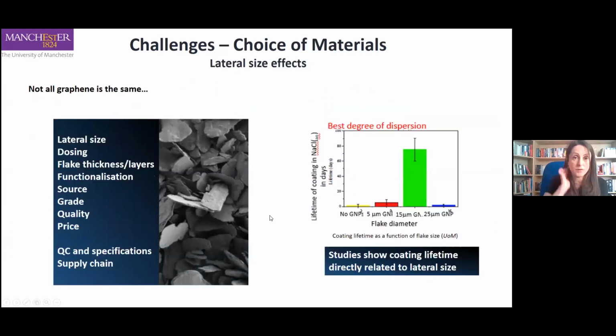And here we're talking about choice of materials again. This is what I referred to just before. It's how the lifetime of a coating is affected by different flake sizes. So this is lateral size. This is work that was done at the University of Manchester to show how a coating exposed to salt solution, to show its lifetime, basically. And there's a clear response based on the flake size. So here, there's an optimum flake size. It's about 15 microns,